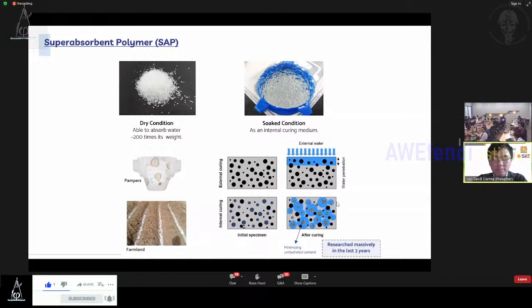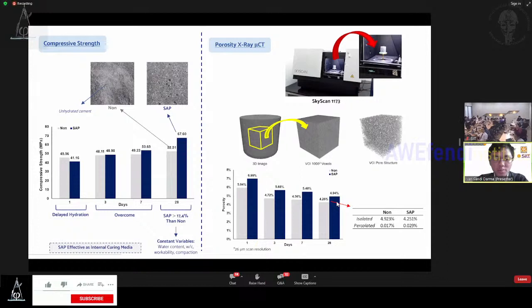In soak condition, superabsorbent polymer is potentially used as an internal curing medium. In this illustration, superabsorbent polymer will release the water that it initially absorbed. Superabsorbent polymer has been researched massively in the last 3 years. For mechanical properties of specimen, compressive strength test is carried out at 1, 3, 7, and 28 days. In day 1, delayed hydration occurs, which can be attributed to the retention of water in SAP. However, starting from day 3, the compressive strength of SAP specimen surpasses the non-SAP specimen. This increment can be attributed to internal curing from SAP, which is evidenced by the failure area of the specimen.